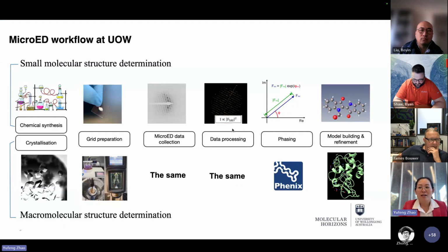So here's our workflow. The top part is for small molecule structure determination, and the bottom half for protein. For our workflow, the data collection and the data processing are quite the same. The difference is at the sample prep and the final structure solving. Currently our workflow is quite mature: with a good sample, with good diffraction, we can quickly solve a small molecule structure with good quality. For protein, the bottleneck is still the sample prep. Every protein is different. This means for every protein, we have to test, repeat, and find the best conditions.